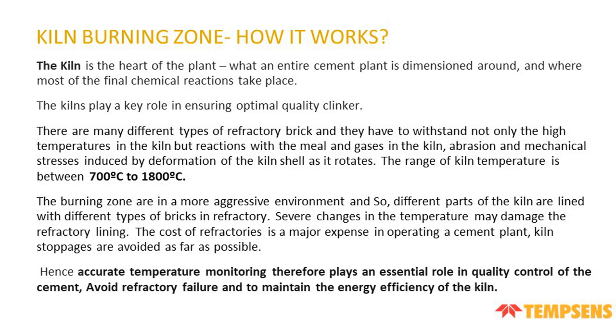The range of kiln temperature is between 700 to 1800 degrees centigrade. The burning zone is the most aggressive environment, and so different parts of the kiln are lined with different types of bricks in refractory. Severe changes in temperature may damage the refractory lining. The cost of refractories is a major expense in operating a cement plant. Kiln stops should be avoided as far as possible. Hence, accurate temperature monitoring plays an essential role in quality control of cement, avoiding refractory failure and maintaining the energy efficiency of the kiln.